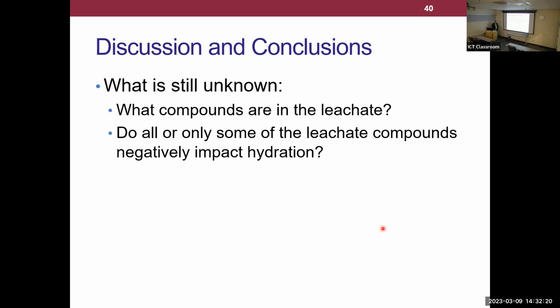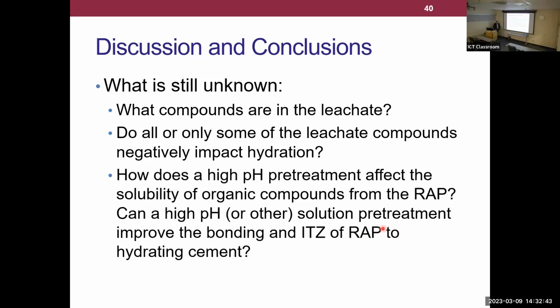The other thing we don't know is, are all of those compounds in the leachate affecting hydration? Maybe there are some compounds in that leachate that don't affect cement hydration whatsoever. Maybe some of them accelerate cement hydration and are beneficial. In the end, we saw that the net effect was negative. The net effect was a retardation of cement hydration.